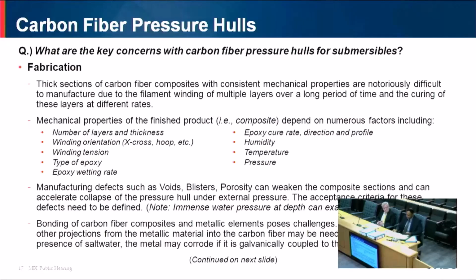Then the type of epoxy resin that is used for creating the composite has an impact on the strength of the pressure hull. So aerospace grade epoxies may not be suitable for high pressure underwater applications, okay? So then there are other factors such as the epoxy wetting rate. That means how much epoxy can you coat on the carbon fiber strands. Then the epoxy curing rate. If you don't follow the correct curing profile, your mechanical strength may differ. Then humidity is another important consideration. So high humidity during curing of the composite can negatively impact the mechanical properties. This is because moisture absorption in the resin can lead to delamination and reduced interfacial strength between the carbon fiber and resin, thus weakening the composite.